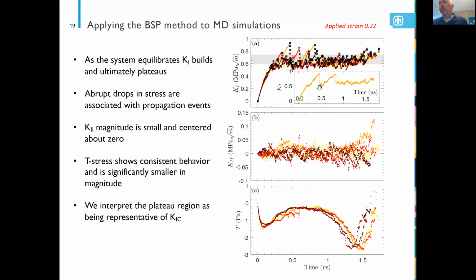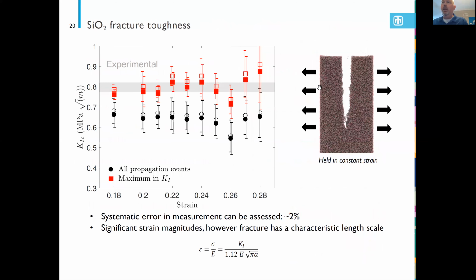And so we can quantify that and plot those as a function of applied strain on the material. As we increase strain values for the material, the crack will actually propagate more readily. So the time frame that the crack remains within the fracture sample actually decreases with increasing strain. However, those maximal values and the average values seem to be somewhat consistent across this strain range. Now I note experimental fracture toughness for silica glass, pure silica glass, is about 0.8 MPa root meter.